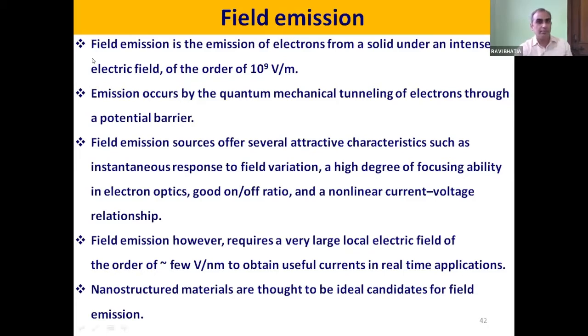The very important thing is field emission occurs from a solid when you apply an electric field of the order of 10 to the power 9 volt per meter, and it is a quantum mechanical tunneling of electrons through a potential barrier. And the important properties one field emitter should have are a good on and off ratio, and a nonlinear current-voltage relationship.